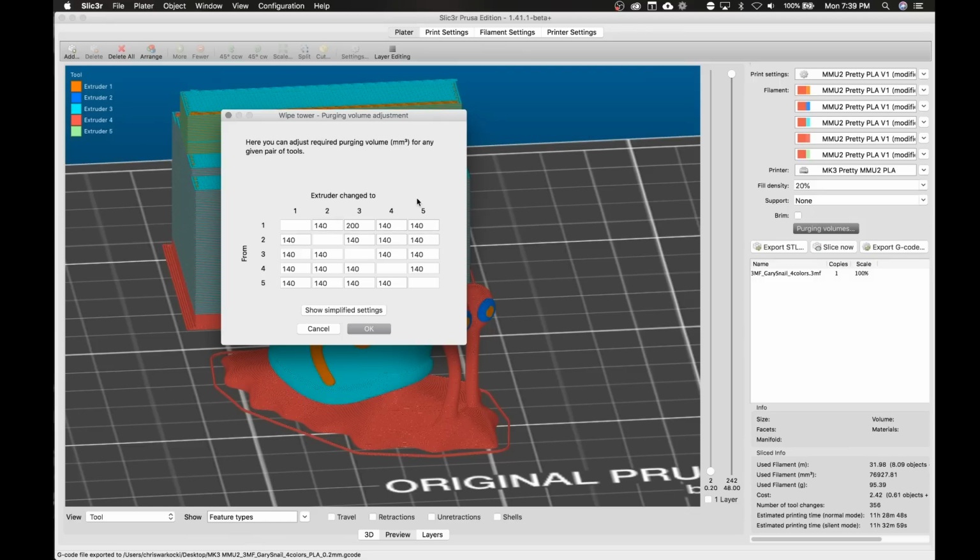But we have the gold. The gold actually was turning quite gray, and we need to do a little bit more purging. And for me, I found out it was actually 210. And I went up to 220, went back down a little bit. I was fine. You can actually follow along. You can look at the purge block, and you can see just how quickly it transfers.